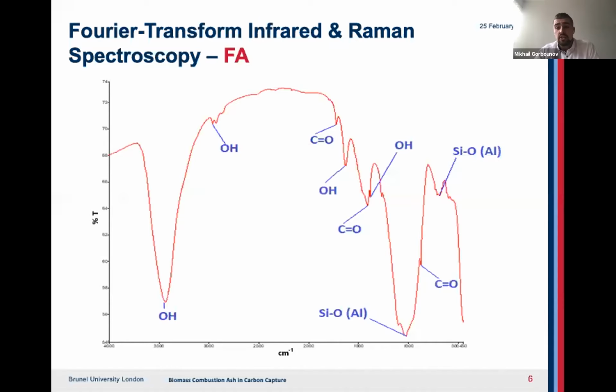do not change their dipole moment during internal vibrations, and therefore these vibrations cannot be easily detected. Nevertheless, the two outermost left peaks and the two other peaks in the middle were ascribed to the OH bond. This functional group is visible on the spectrum due to one of two reasons. It is either denoting the presence of physical water on the sample, or it occurs there naturally due to the hydroxides present in the ash.